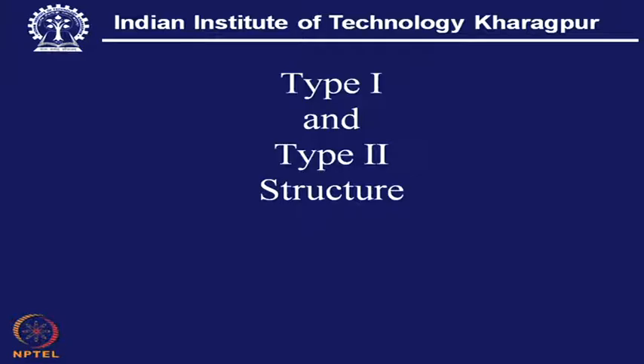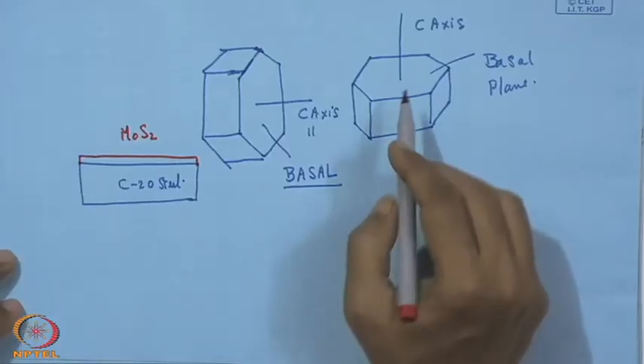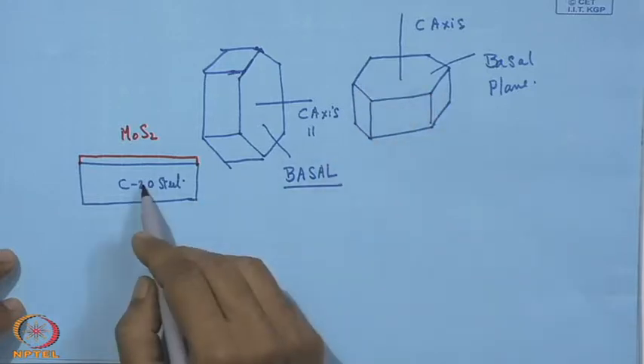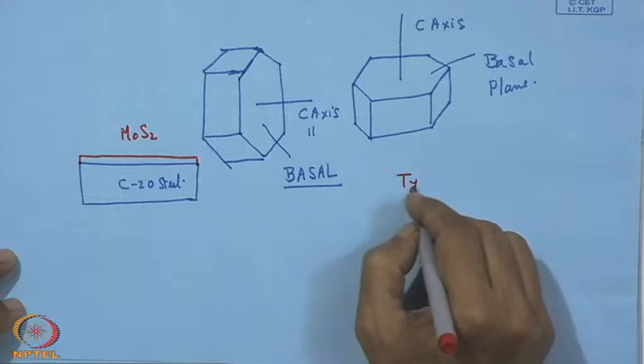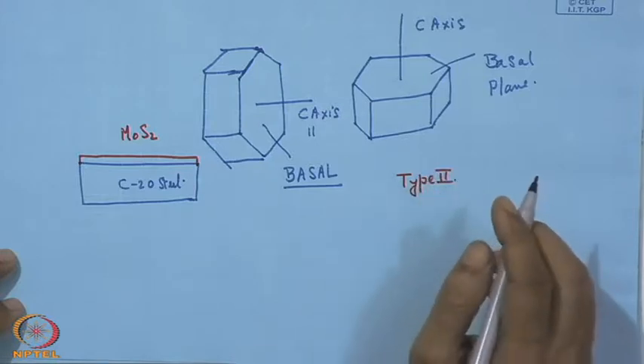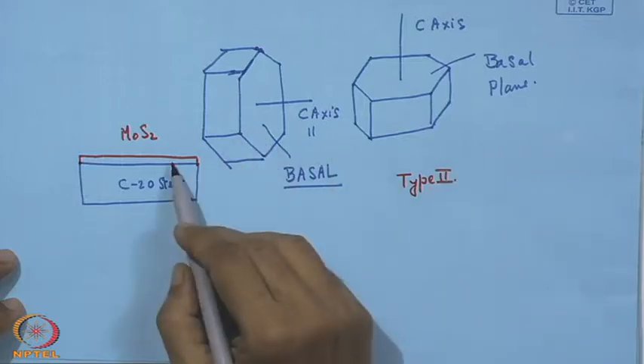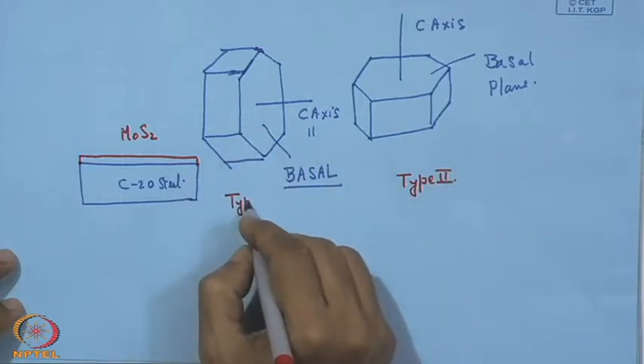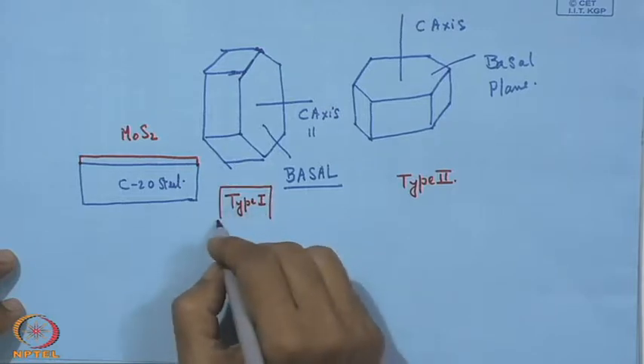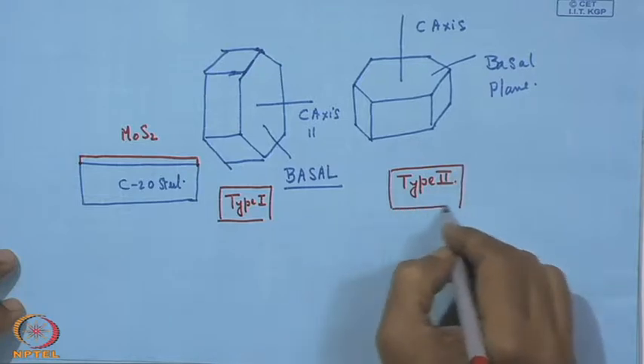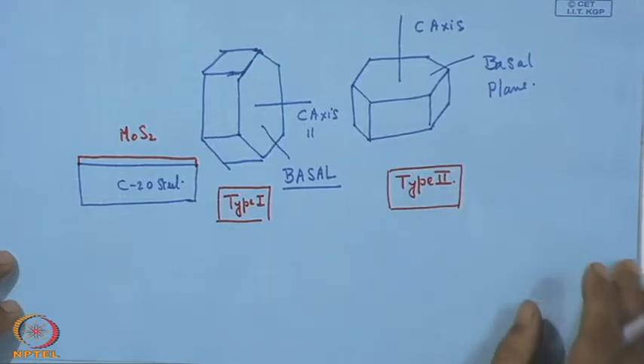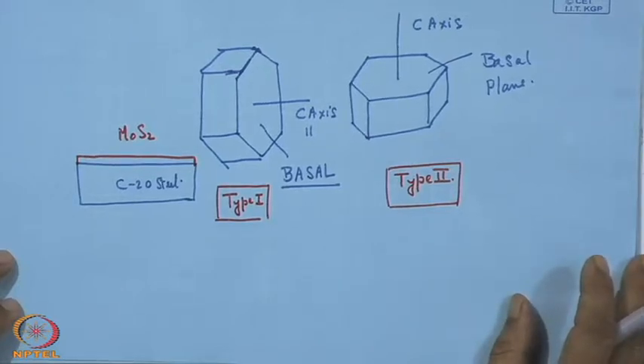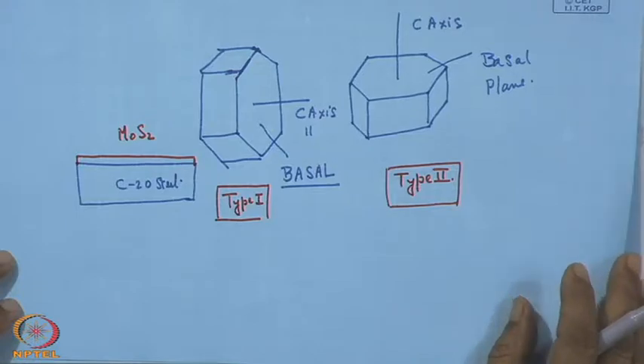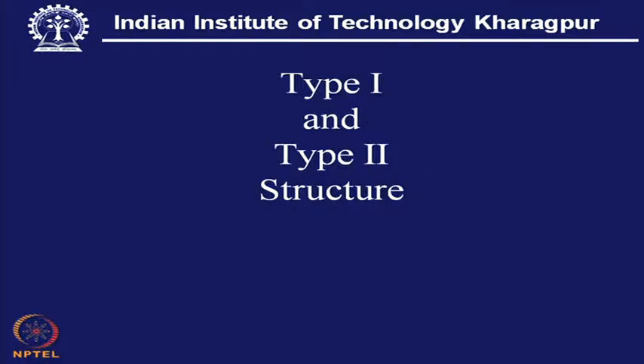Now, we have type 1 and type 2 structure. For this we can refer to the previous figure. If we have the basal plane parallel to the substrate surface, then we call this type 2 structure. And when the basal plane is perpendicular to the substrate surface, we call it type 1 structure. So, obviously, our choice will be type 2 structure, considering that a low value of friction is most desired, and this is for the purpose of having the best performance of any component or wear part.